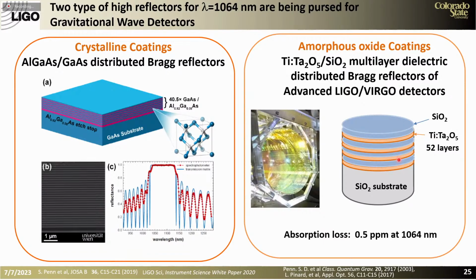Now, the two technologies that are being envisioned for coatings for gravitational wave detectors are crystalline coatings that are based on gallium arsenide distributed Bragg reflectors, and amorphous coatings. And right now, the coatings that are in the interferometer are a combination of tantala doped with titania, and silica. And the challenge of using the crystalline coatings is actually a technological challenge. I mean, these coatings can be easily made of excellent quality. However, the issue is that they cannot be as large as